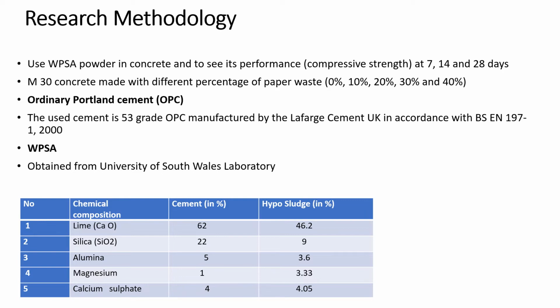M30 concrete was made with different percentages of paper waste from 0 to 40%. Ordinary Portland cement was used in the experiment, and the waste material, the ash, was obtained from the University of South Wales. Here in the table, you can see the composition of the cement and the hypo sludge which we have used in our experiment. For example, if I look at the first item, the lime or calcium oxide, in cement we have 62%, and the waste material which we have used has 46.2%. So it's not quite equal, but roughly they have the same content.